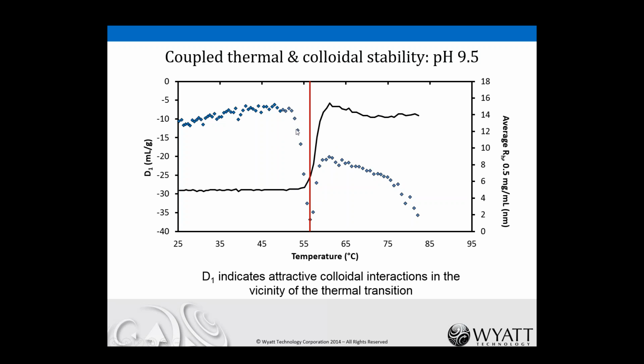Interestingly enough, D1 actually begins decreasing several degrees before the onset of aggregation. That means that as the molecules begin unfolding and exposing their hydrophobic cores, they become self-attractive, but not yet to the degree to which they aggregate. That self-attractive behavior is reflected in the decrease in D1. And finally, where the aggregation starts occurring, we have a negative maximum D1. That means there's the most self-association. As soon as that aggregation occurs, those hydrophobic cores will now be hidden from the solution and hidden from the other molecules in solution, and therefore those molecules become less self-attractive, and D1 increases further. So that's an interesting way to utilize dynamic light scattering to get some more in-depth information about the behavior of the molecules around their unfolding and aggregation transitions.